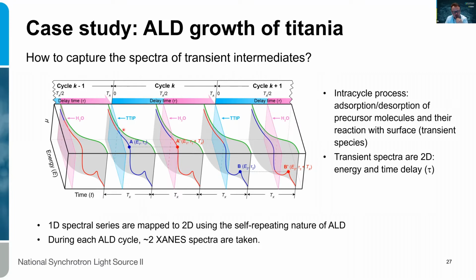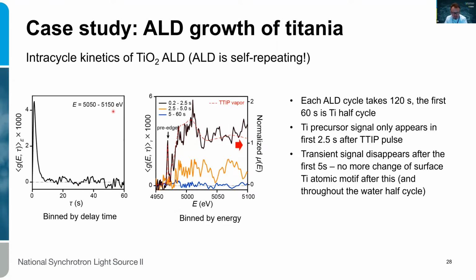So we're not looking at the entire spectrum, we're looking at parts of the spectra now and processing them separately. One important thing is that ALD is presumably a self-repeating process. So every next cycle is exactly like the one before. And so we can essentially bin the data by delay time from the injection of the precursor.